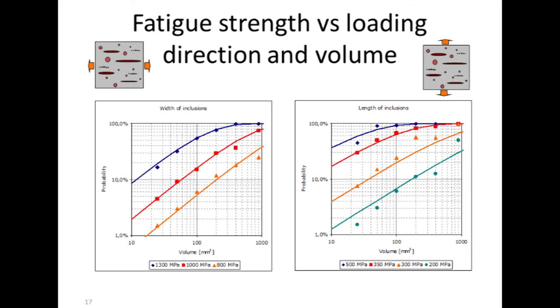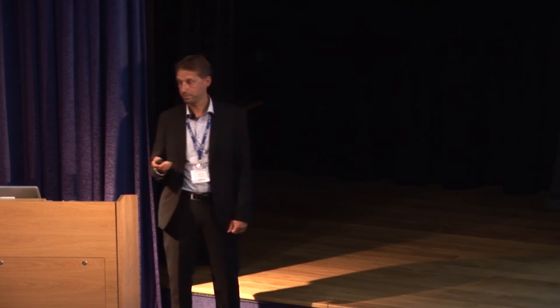That's a dramatic difference. And you also have a quite dramatic shift if you go and test a bigger volume. If you go up and test 1000, for a 50%, it drops down to somewhere around 900. So pick a number.